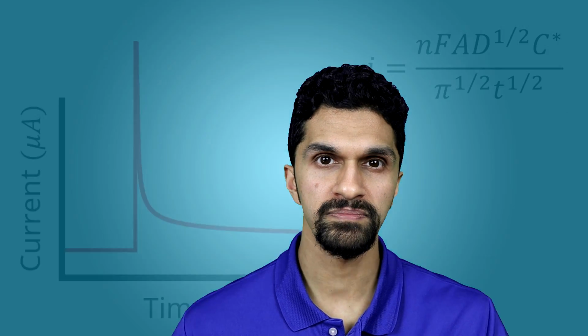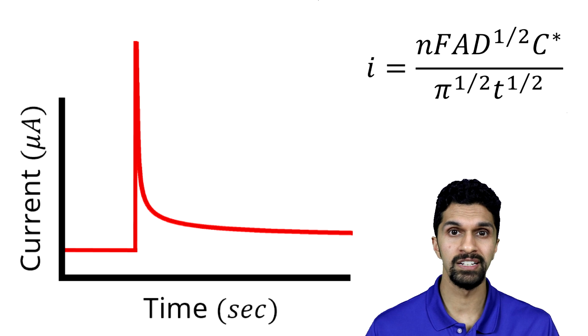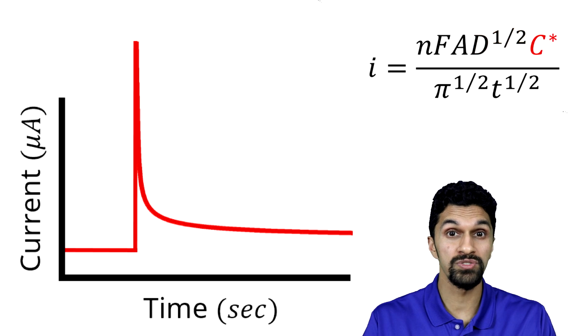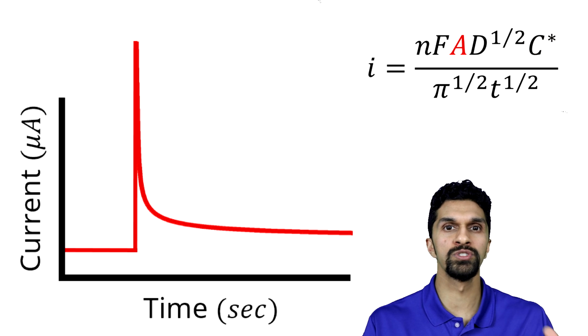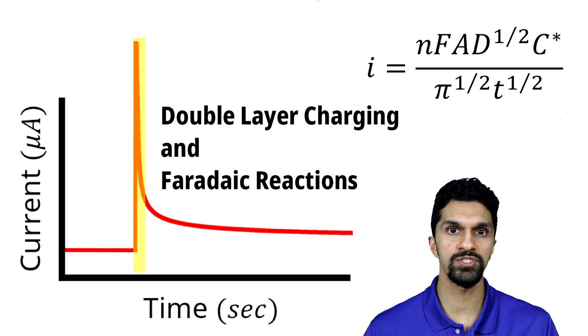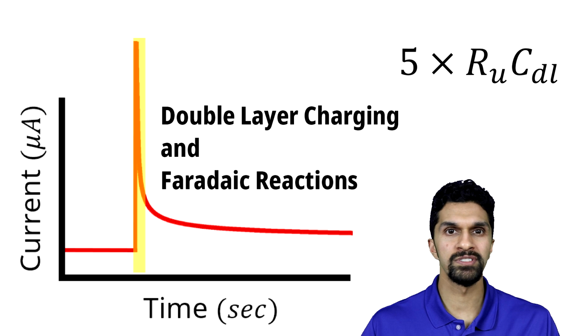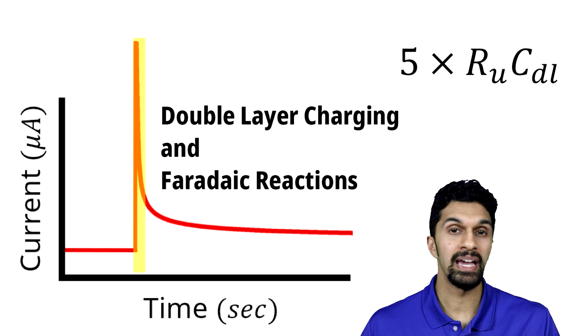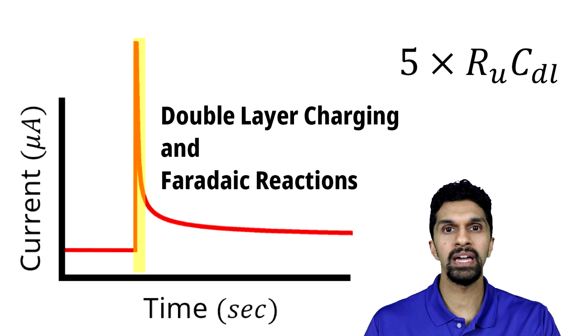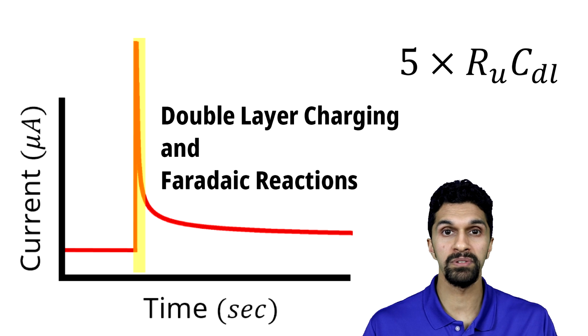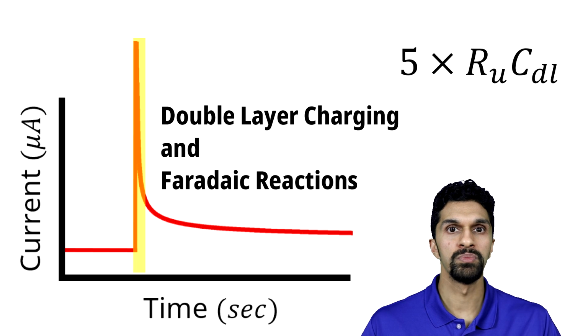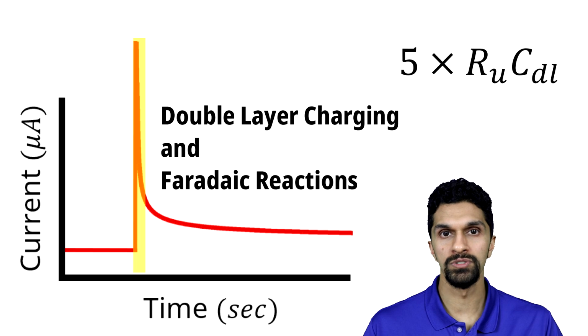However, the Cottrell equation and the Cottrell plot only consider current associated with a diffusion-controlled redox reaction. It does not take into account the current associated with electrical double-layer charging. So if we want to use our chronoamperometry data to calculate things like the diffusion coefficient, or the concentration, or the area, we would need to exclude data points that are convoluted by electrical double-layer charging. Remember earlier, the electrical double-layer is basically completely charged after 5 RC, and depending on your electrochemical system, that could be several microseconds or several milliseconds. But if we exclude that data in the first few milli or microseconds of our experiment, it excludes that 5 RC, we should be good. We can use that data to do calculations.